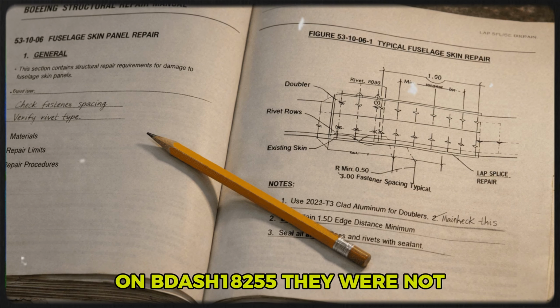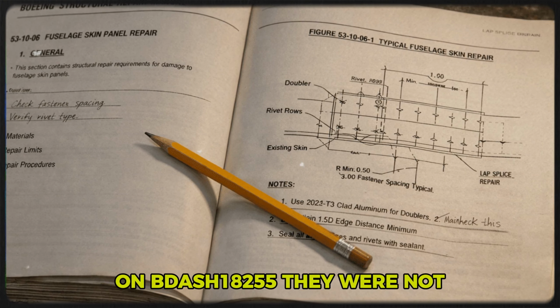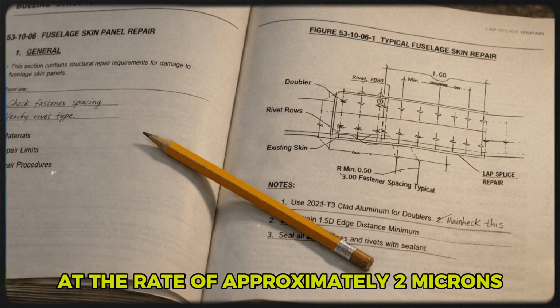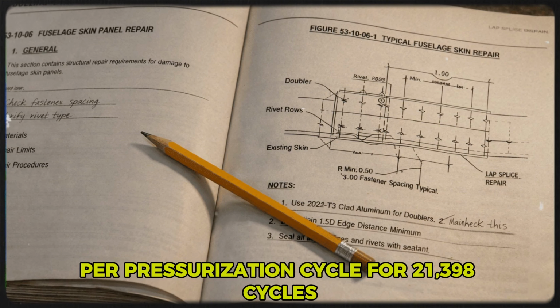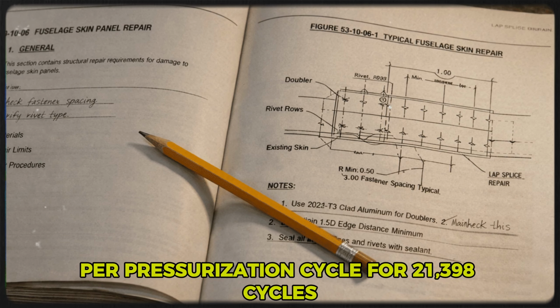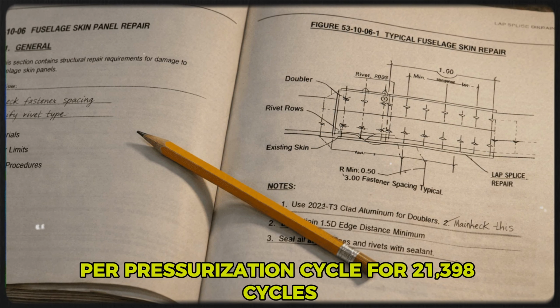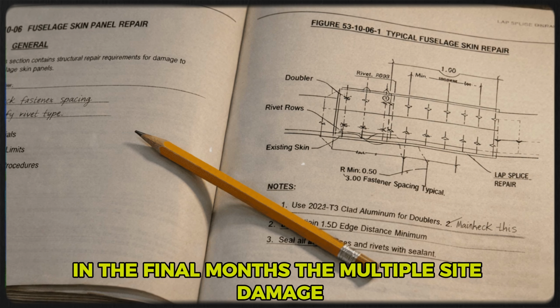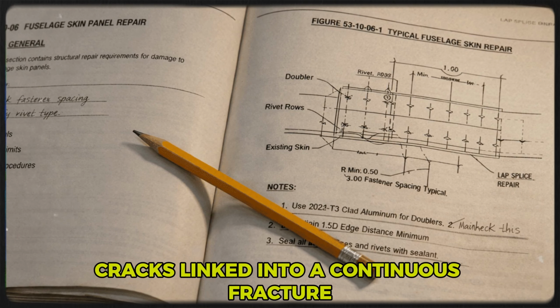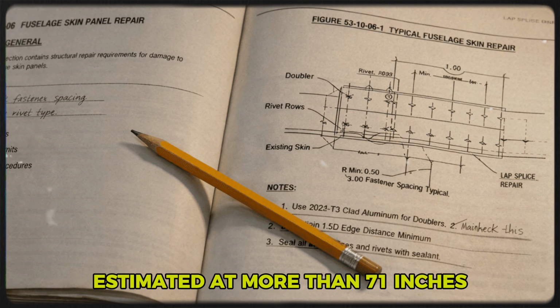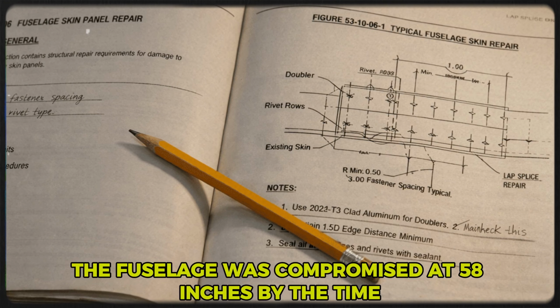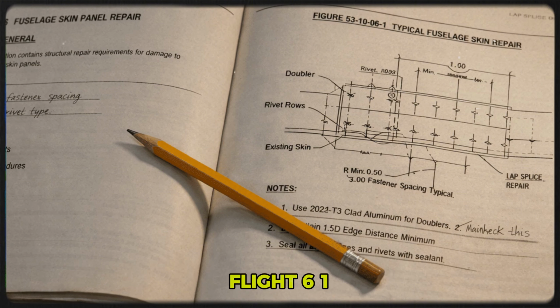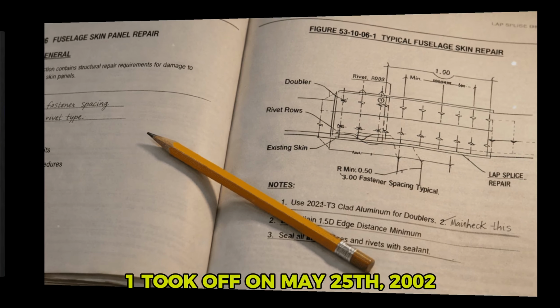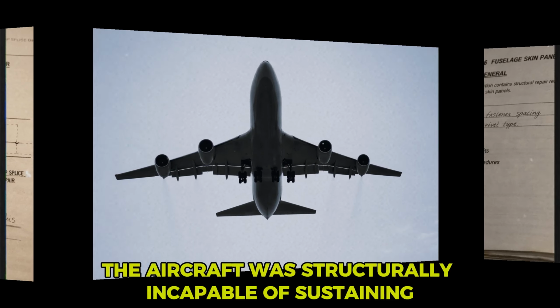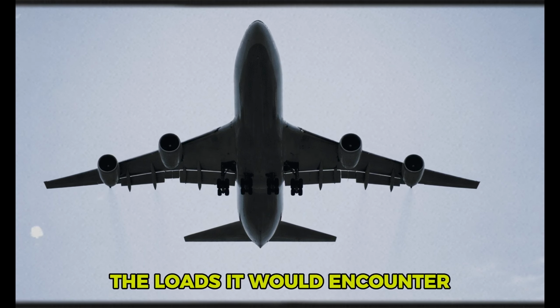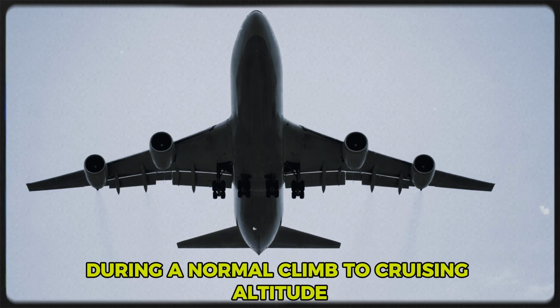On B-18255, they were not. The crack grew beneath the doubler at the rate of approximately 2 microns per pressurization cycle. For 21,398 cycles in the final months, the multiple site damage cracks linked into a continuous fracture estimated at more than 71 inches. The fuselage was compromised at 58 inches. By the time Flight 611 took off on May 25, 2002, the aircraft was structurally incapable of sustaining the loads it would encounter during a normal climb to cruising altitude.